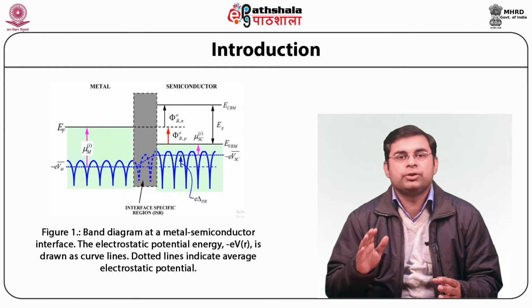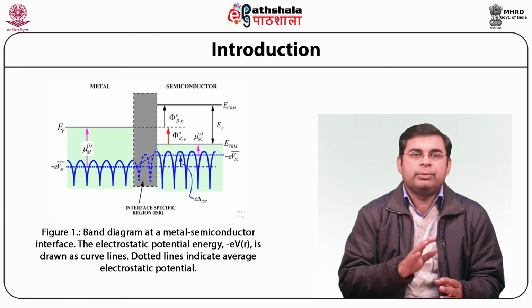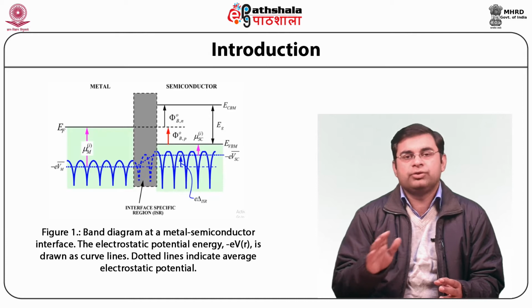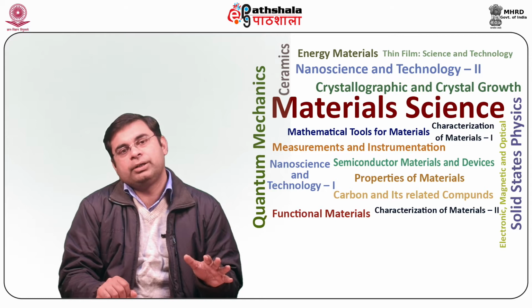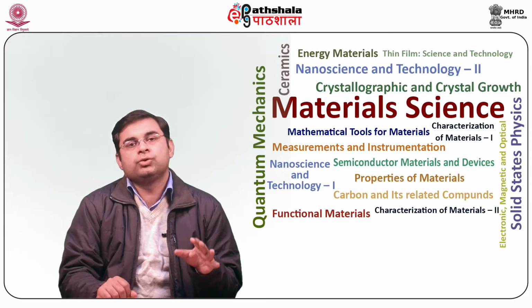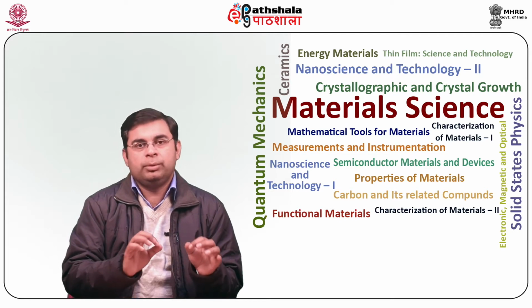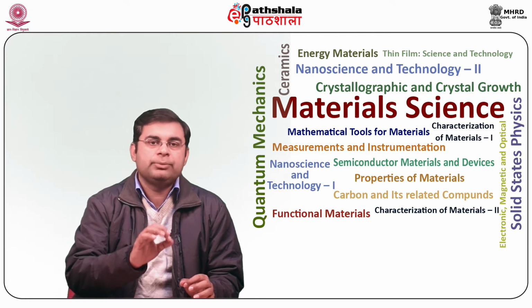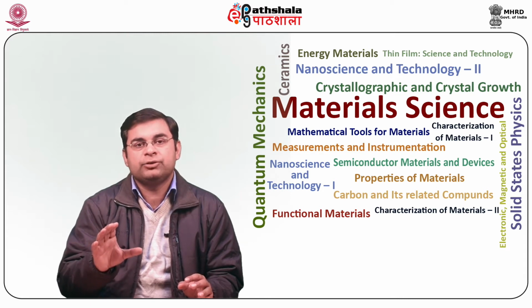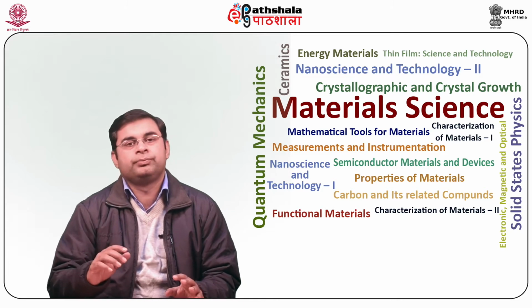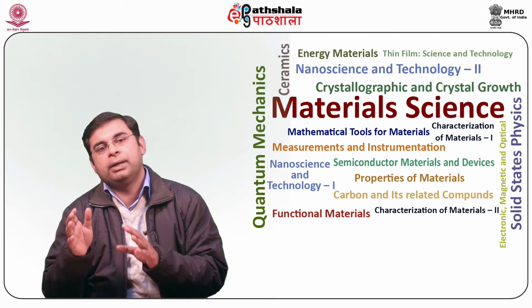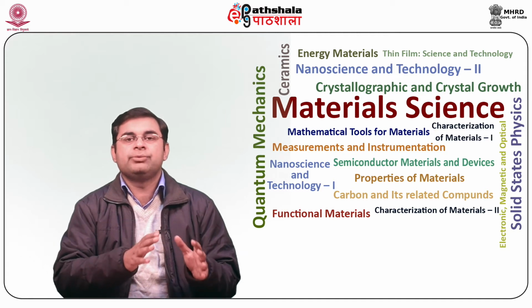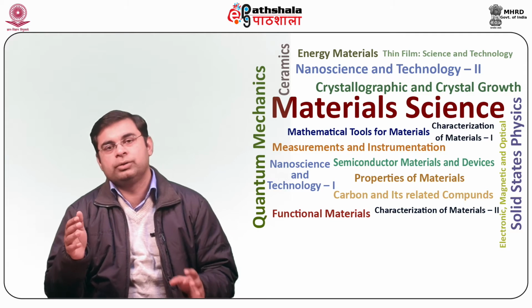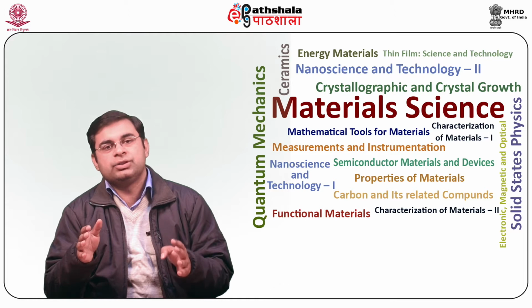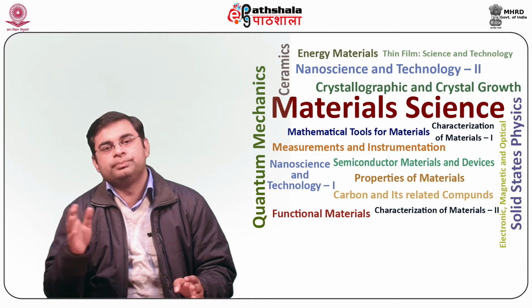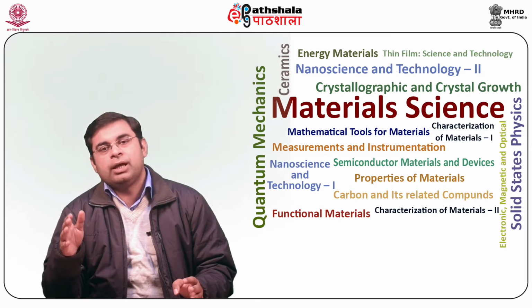The set of electronic states responsible for electrical conduction in the semiconductor depends on the type of doping of the semiconductor. In case of n-type semiconductor, the electrons present close to the conduction band minimum, that is CBM, contribute to the electrical conduction. Whereas in p-type semiconductors, the holes available near the valence band maximum, that is VBM, contribute to the electrical conduction. Because of the presence of the fundamental band gap, the lowest lying states for an n-type semiconductor that can communicate with electrons in the metal are at energy level phi Bn raised to power 0 above the Fermi level, as shown in the figure.